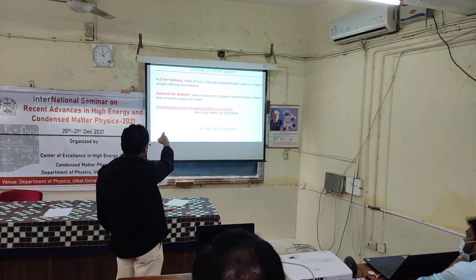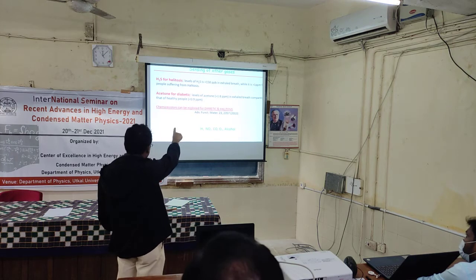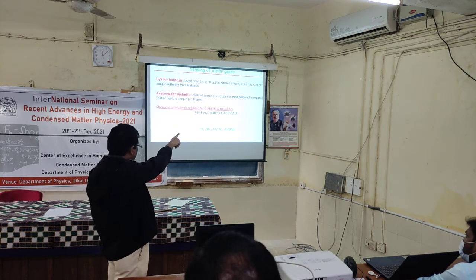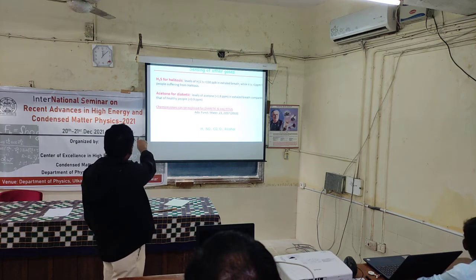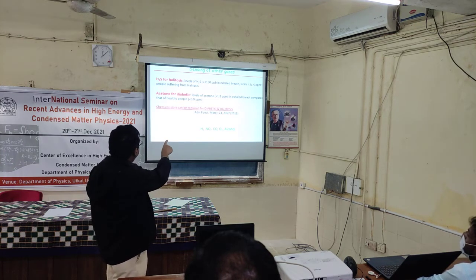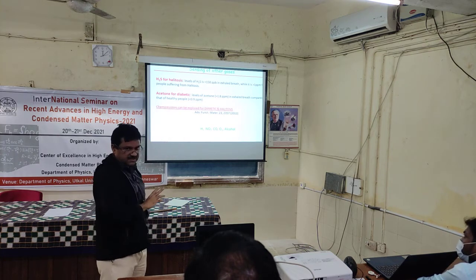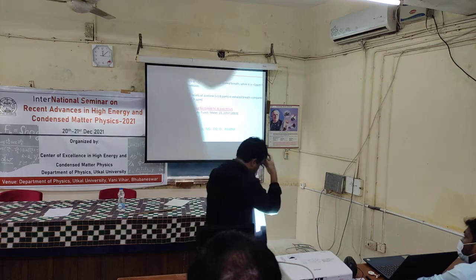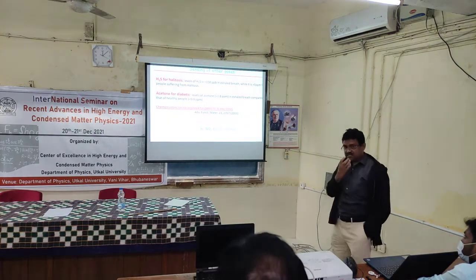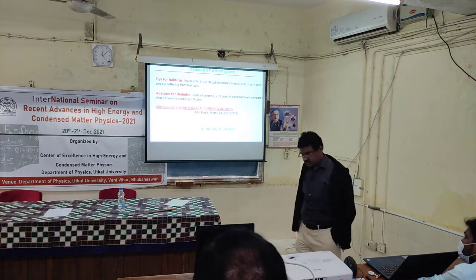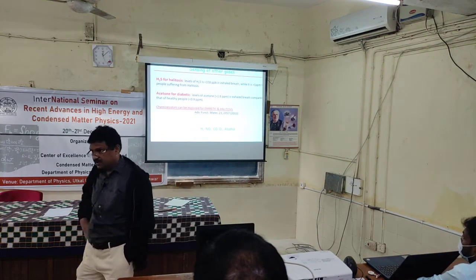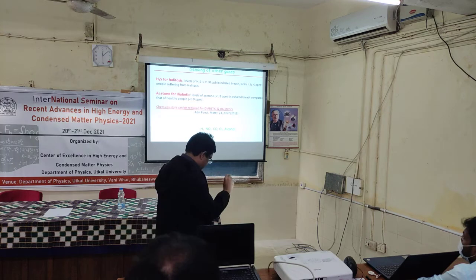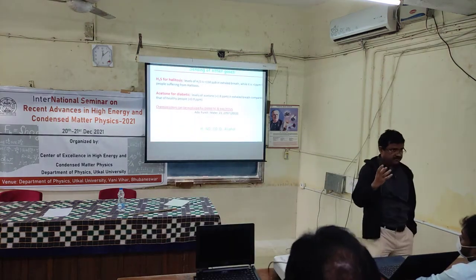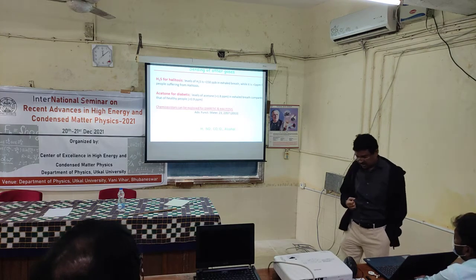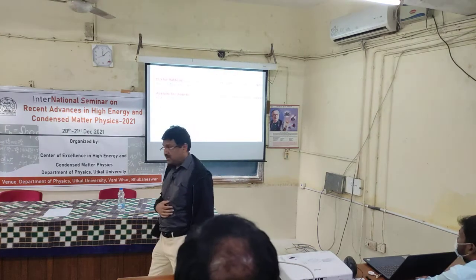The level of H2S is less than 100 ppb in the exhaled breath of a normal human being, whereas it is greater than 1 ppm, so more than 6 times, for people suffering from halitosis. Similarly, you can monitor acetone. The level of acetone is less than 0.9 ppm for a healthy person, and more than 1.8 ppm for people suffering from diabetes. So by analyzing the exhaled breath, you can check whether you have halitosis or diabetes. I have given you 2 examples of how important it is to monitor the gas in our exhaled breath or in an environment.